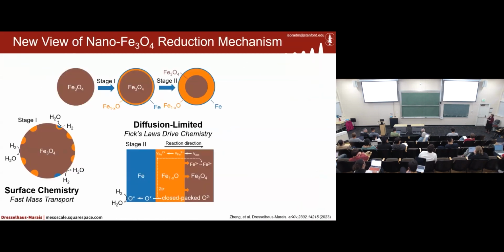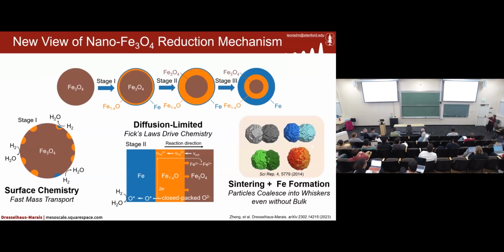So our view of this is really that what we've been able to demonstrate is fast transport of surface chemistry at the beginning, then diffusion limited chemistry in the middle in stage 2, and finally the sintering and iron formation that ultimately is associated with the whiskering at the nanoscale.